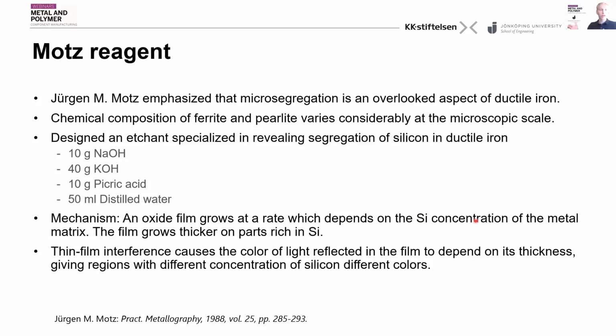So that after a while of etching with this etchant, the film is thicker in the parts that contain more silicon. Then light interacts with the film through thin film interference, which causes films of different thickness to reflect light of different colors, which then reflects the underlying silicon concentration.